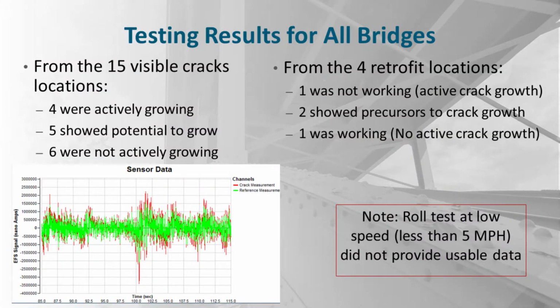What were the results of this test? Well, the first one is the roll test at low speeds did not provide usable data. When the vehicle goes very slow, the way the passivation breaks and reforms, it's kind of quick. So if the truck or car is going very slow, the sensor will detect it as almost like a quasi-static loading. So the passivation layer will have time to reform, and the reading coming out of that won't be very accurate. But I don't think we have that problem in current days, since all the people seem to be in a hurry, so they're always speeding. So we're fine in that regard.